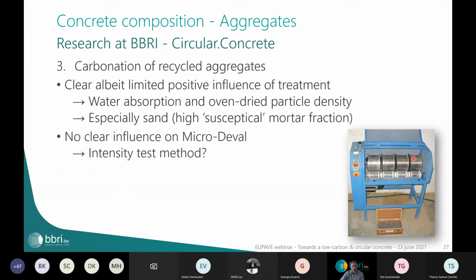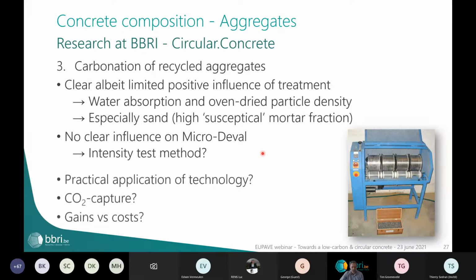However, no clear influence could be seen on the mechanical properties of these aggregates, and perhaps this has to do with the intensity of the test method. And so the slight enhancement in porosity and density perhaps doesn't have a very high influence on these properties. So it seems interesting, but again, we have to look at the practical application of this.